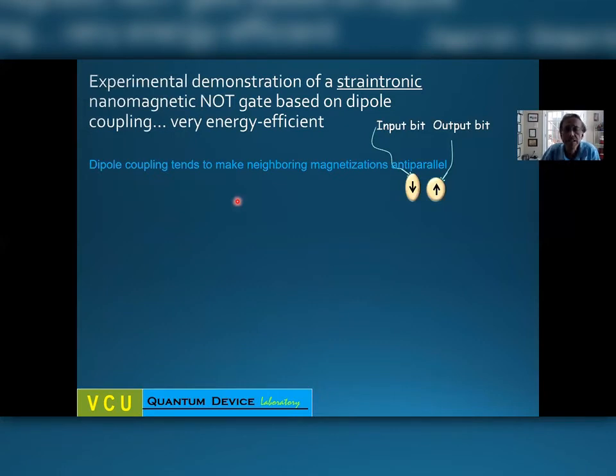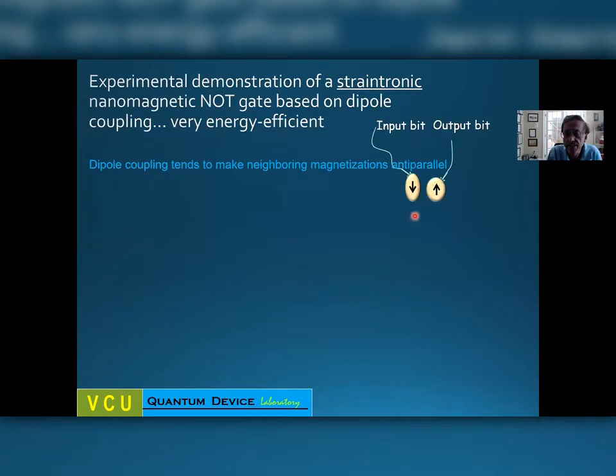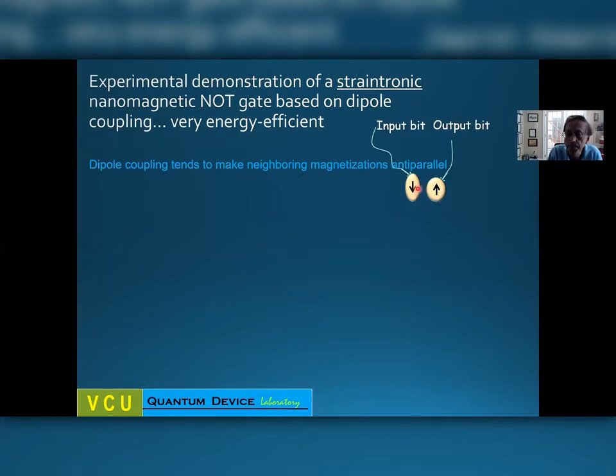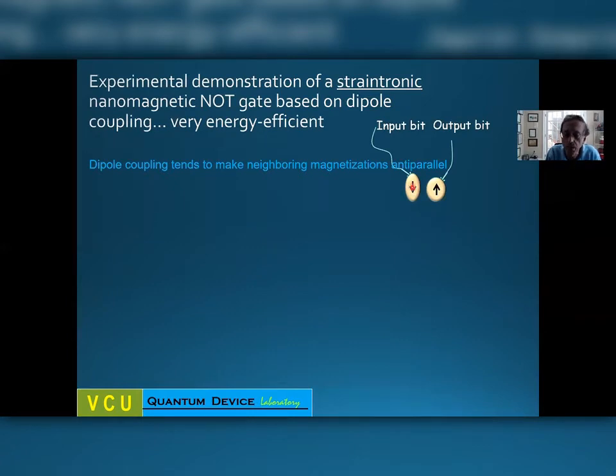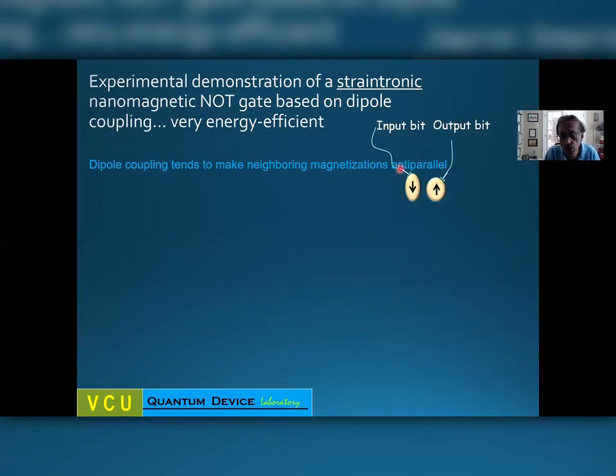The first thing we did was implement something useful with StrainTronics — a NOT gate or inverter. The way you do that is with two nanomagnets: one is more shape-anisotropic or elliptical than the other. The magnetization states in these two nanomagnets encode the input bit and the output bit. If you place the two magnets such that the line joining their centers is parallel to the minor axis, dipole coupling will make the magnetizations mutually anti-parallel, so the output is the logic complement of the input — an inverter or NOT gate.